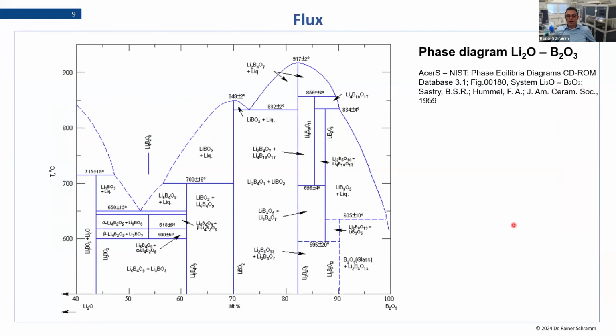Typically today we use lithium borates, and you could also use borax, sodium borates, or just boron oxide. This is also okay, but typically the lithium borates are used. If we want to see how the different fluxes, the different lithium borates, behave, we need to have a look at that phase diagram. So how do we read that? Here we have the temperature, and here we have the amount of boron oxide. The lithium borates we typically have are lithium tetraborate or lithium metaborate, a mixture between lithium oxide and boron oxide. We read this in this way: everything higher than this line is liquid phase, and this is all solid phase.